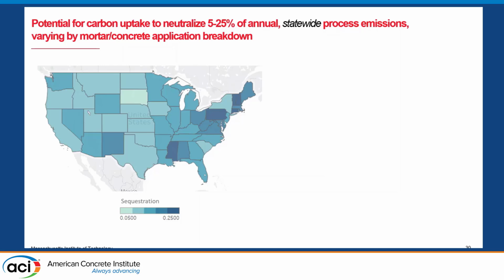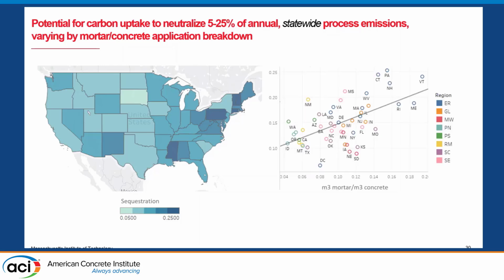So that plot shows the percent sequestration of calcination emissions by carbon uptake based on our estimate. The lightest blue is the 5% value, and the darkest blue represents the 25% value. And there's a variation across the states, which relates to factors like the construction rate and other information as well. But one key piece of information that we found that had a high impact on these variations is the breakdown of mortar to concrete applications.